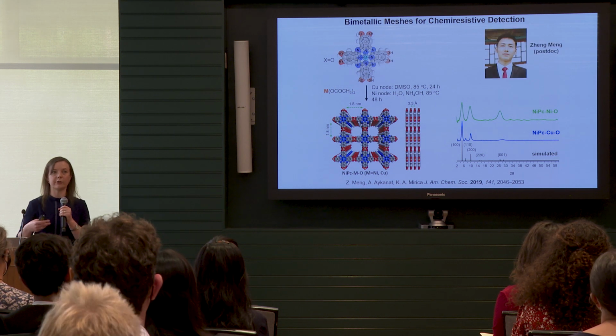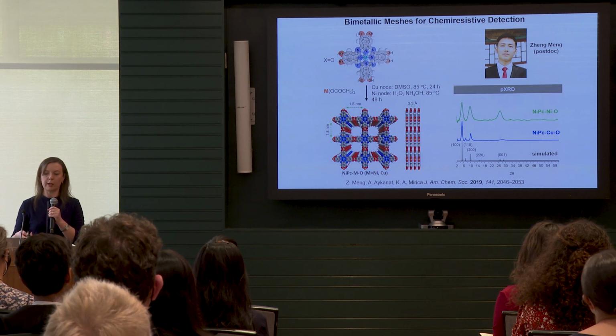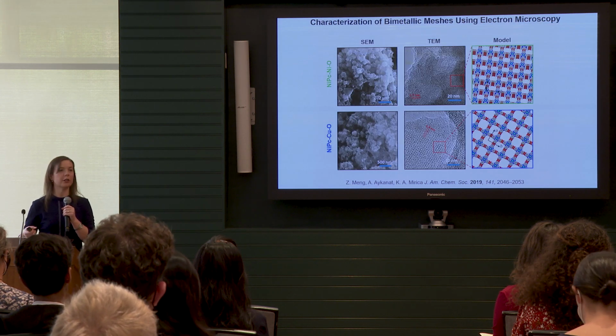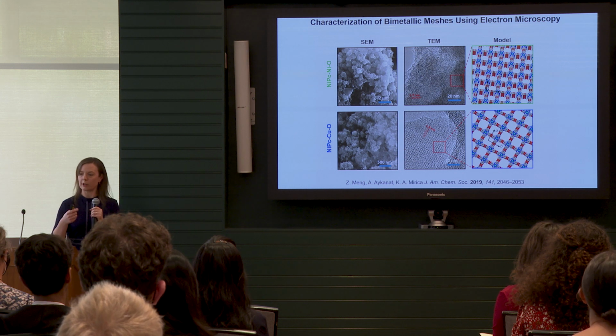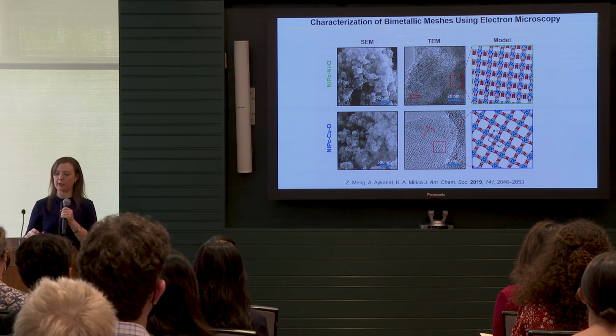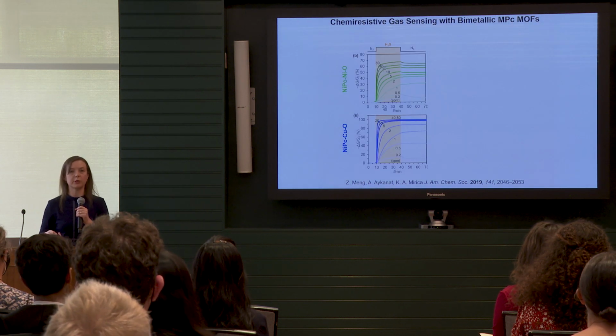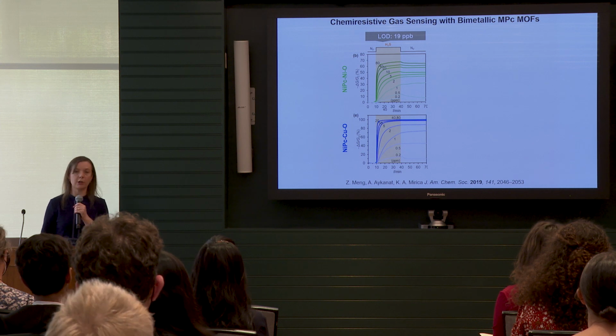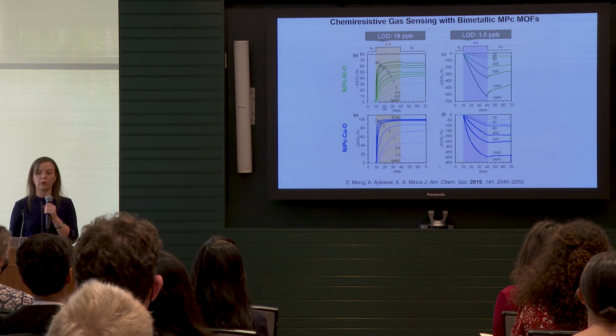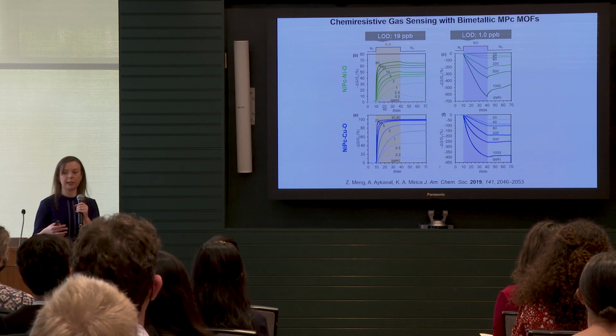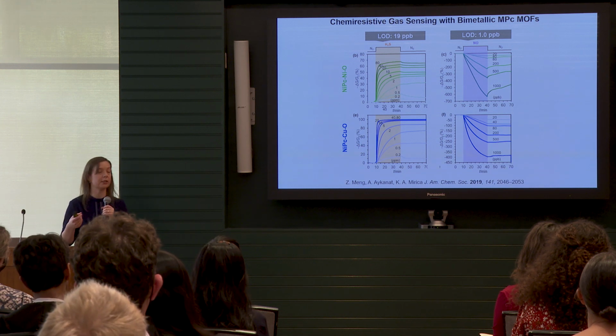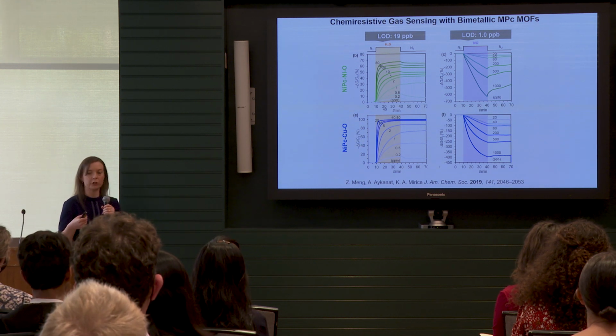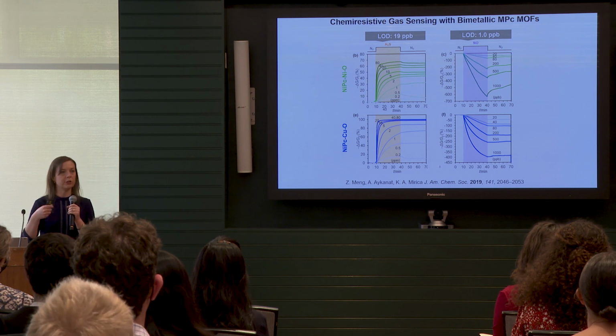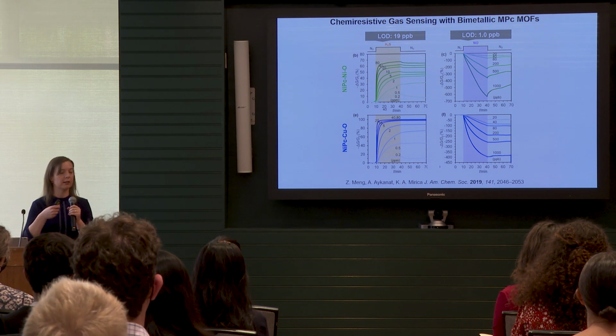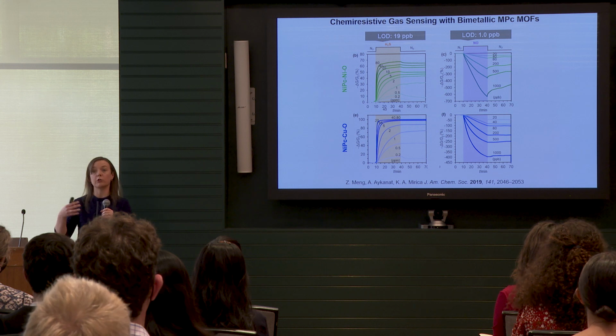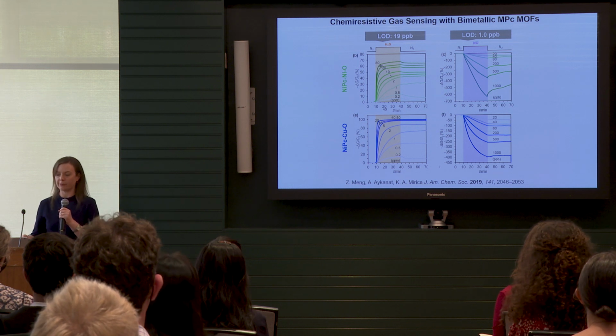But by utilizing solvothermal synthesis, we're able to achieve a crystalline material that exhibits particle-like morphology and also can be exfoliated into thin sheets. Placing this material into chemical sensors, we're able to achieve now much lower detection limits. And we attribute these detection limits in the part per billion regime for hydrogen sulfide and nitric oxide to the unique structure and the bimetallic system that we're employing, so to the molecular design of the material itself.